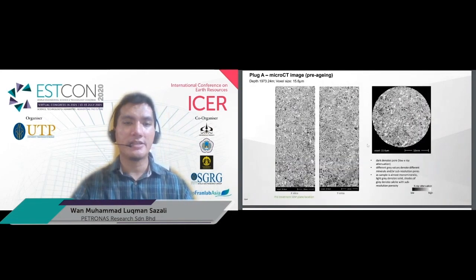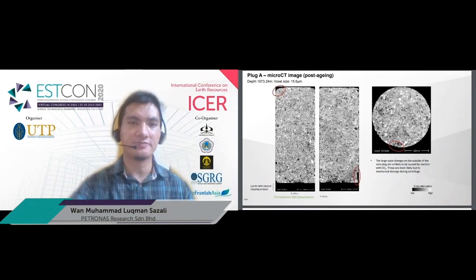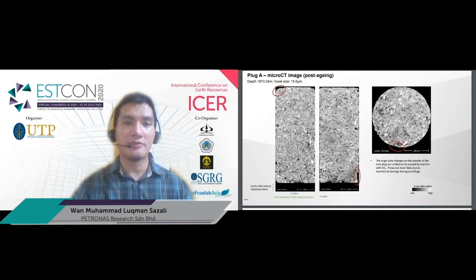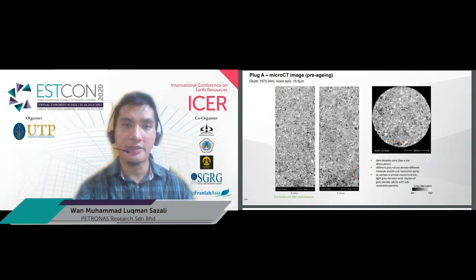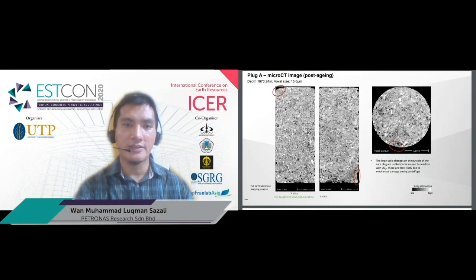Okay, the figure here is a series of micro-CT images taken from the X slice, Y slice, and also Z slice. As you can see here, we were able to produce a high resolution image at 15.6 micron using a 1-inch sample. And here is the post-aging micro-CT image that was scanned after the sample was saturated, centrifuged, and aged with CO2. As you can see here, there are indeed some changes happening before and after the analysis.